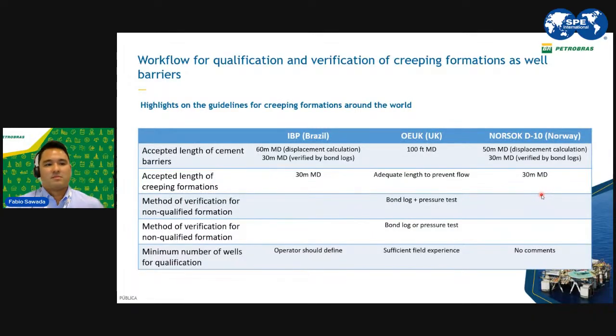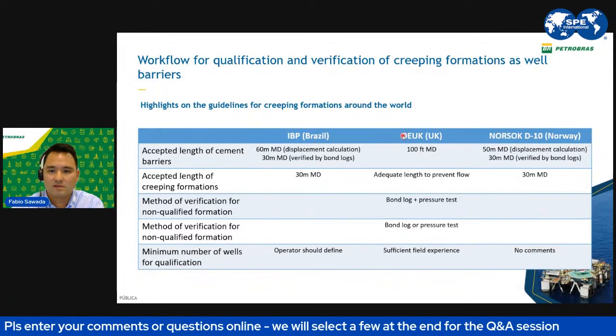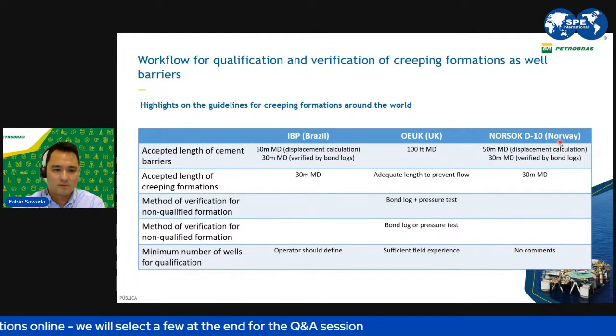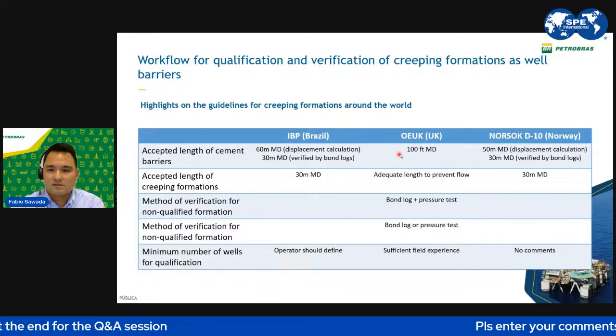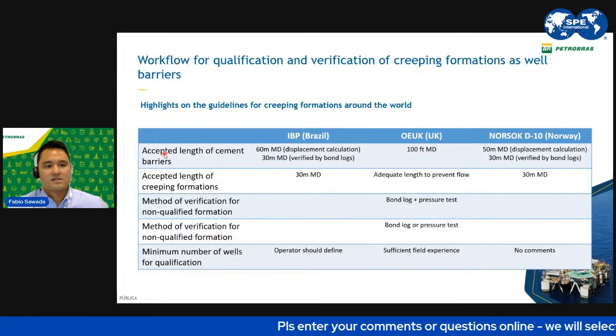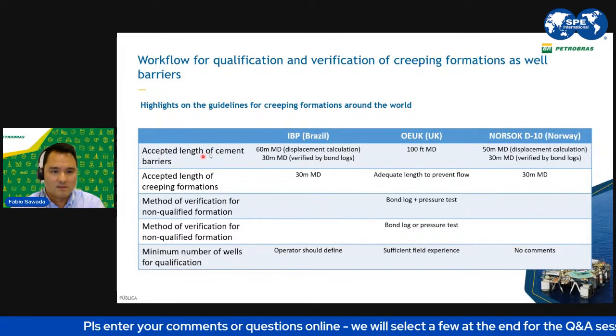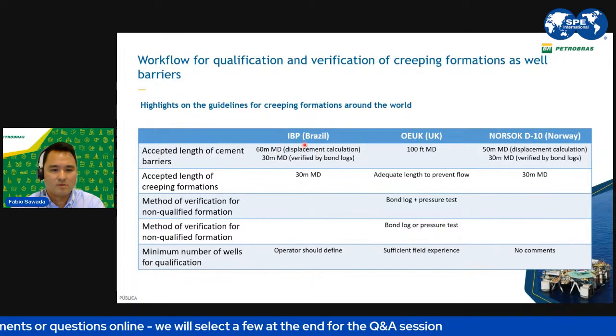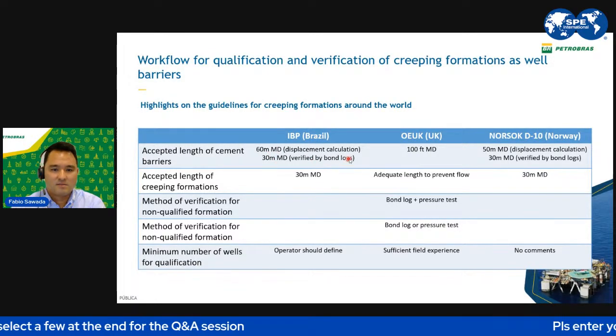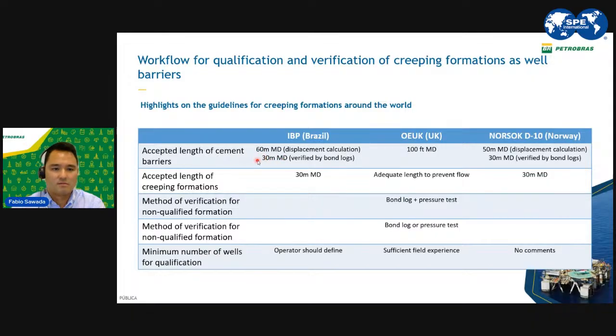So I'm also bringing some highlights on the guidelines that we have around the world. We generally use the Brazilian guideline, but we know that we have a guideline in the UK, and we have also a guideline in Norway. And we see some differences here. In the first line here, we see accepted length for cement as a barrier. In Brazil, we understand that if we can verify the cement by bond log, a 30-meter MD length would be enough. But if we use a calculation only by the cement job parameters, the displacement calculation, we should need a higher length for the cement.